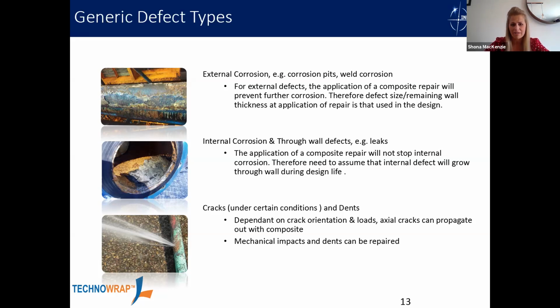And also cracks. So ultimately that depends on the orientation and the loads. If you think about axial loads, they would obviously continue to propagate out with the sides of the composite repair. If it's in the circumferential position, then it's not such an issue. We can design for a full circumferential slot. And we can also repair mechanical impacts and dents.